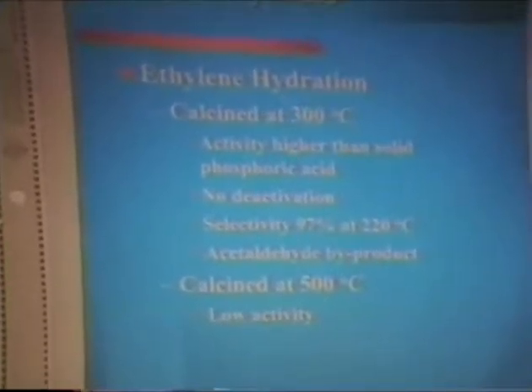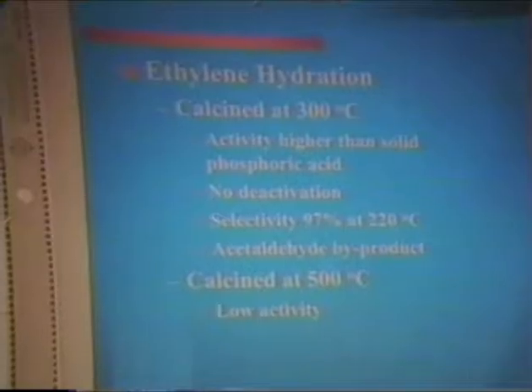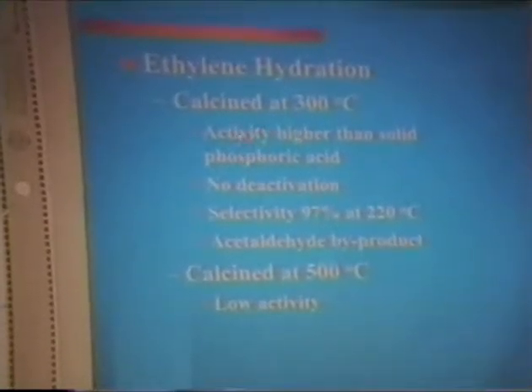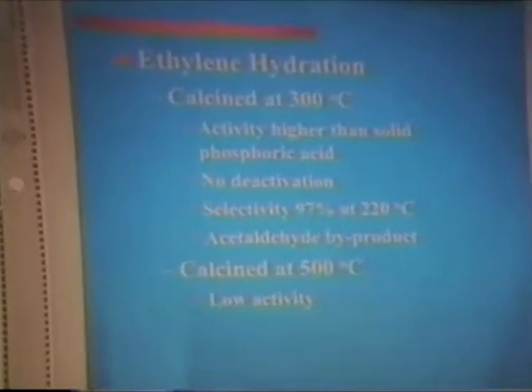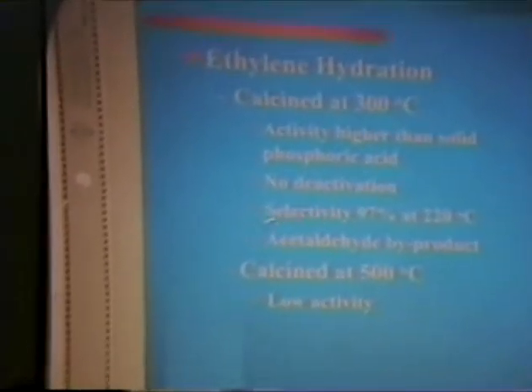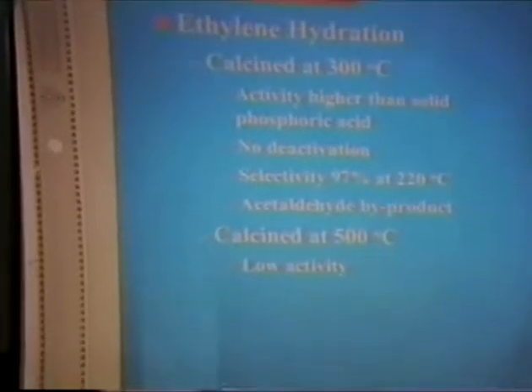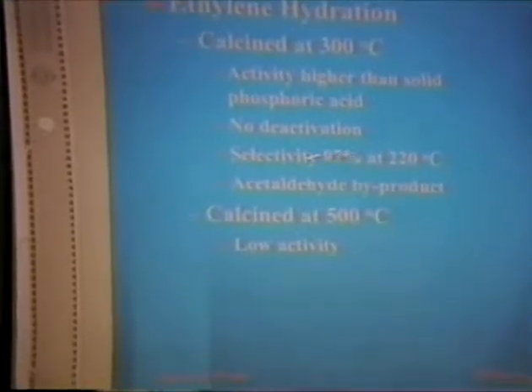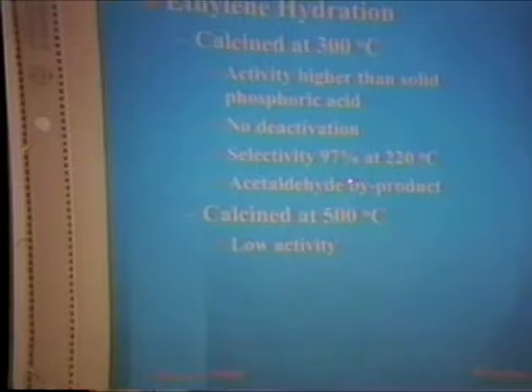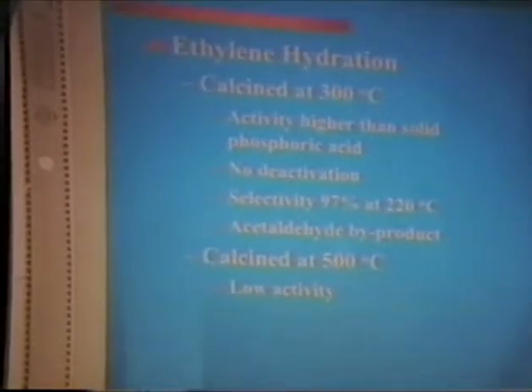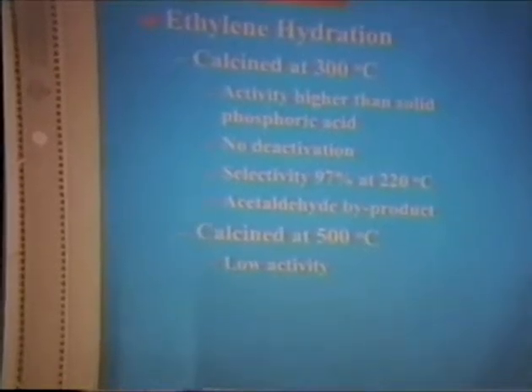And here's an example, again out of Tanabe's work, where the hydration of ethylene, where the niobium pentoxide has been calcined at 300 C. The activity is actually higher than that of the solid phosphoric acid catalysts that are used commercially. There's no deactivation over time, partly because you're continuing to put water in the system, and then your selectivity is also high. You do have some small amounts of byproduct. When you calcine to 500, or if in your operating conditions you get up to 500 C, you're going to lose activity.